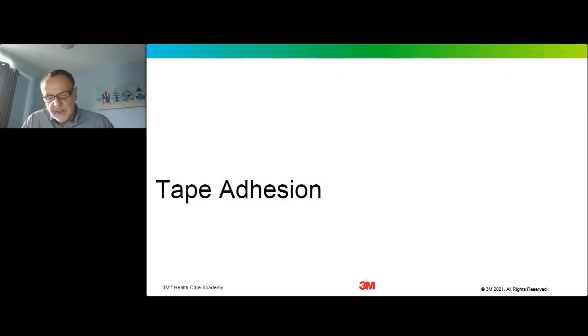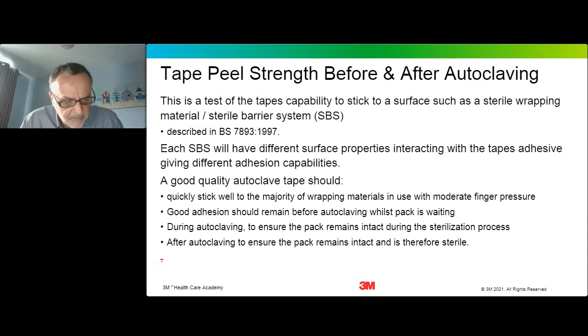So let's now consider tape adhesion. Well, tape adhesion before and after autoclaving is more or less describing the adhesive properties. So peel strength is describing the adhesive properties of the tape. And it determines how well the tape sticks to a specified surface, which might be, for example, a sample of flexible wrapping material. Now, as I stated earlier, each sterile barrier system will have different surface properties, and the tape will interact with that surface in a different way. A good quality tape should stick well to the majority of wrapping materials that are going to be used after application by moderate finger pressure. So you shouldn't need to put the whole of your body weight on the tape in order to get it to stick.